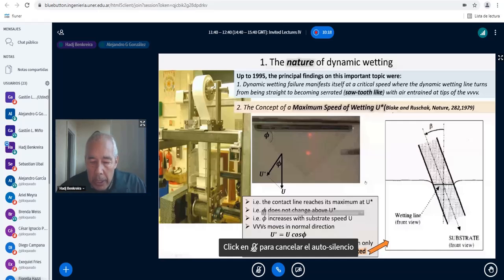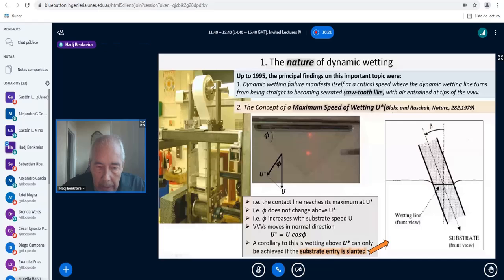So the situation is that you have, as you see in here, the wetting line trying to advance normal to itself. And when you look at this, you will have the maximum speed of wetting in here, which I'm calling U star. And this is what two very famous researchers in dynamic wetting, Blake and Ruschak, in 1979, postulated. They postulated that there is a maximum speed of wetting.